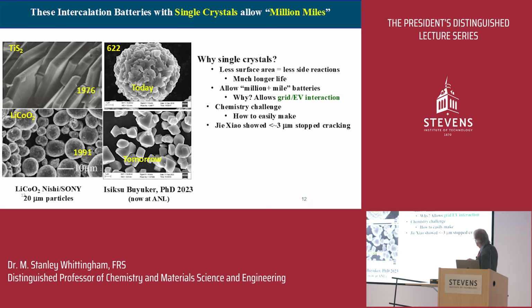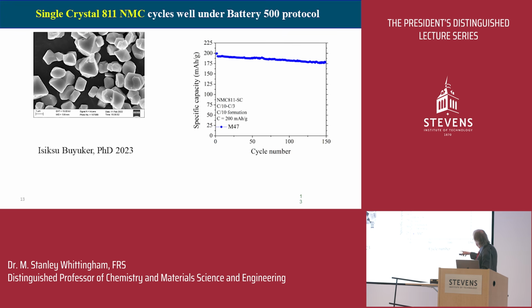The chemistry challenge is how to make these single crystals in tonnage quantities. We're working on it, and clearly the Chinese are rushing us ahead as fast as they can. And if we keep these crystals below about 3 microns, they don't crack. So what do I mean by cracking? I'll show you in 2 slides, but just show you these single crystals. Here's the capacity. Cycle it 150 times, there's no loss of capacity. So single crystals work. The question is, can we make it economic?